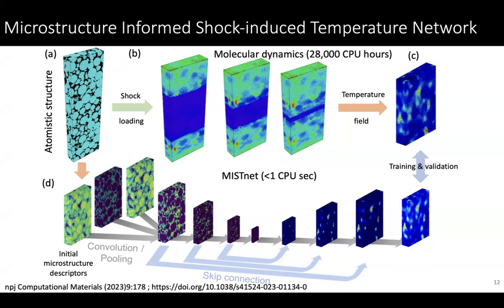But what these guys do is they have convolutional layers. So the convolutional layer looks at, in this particular case, a 3 by 3 by 3 matrix of the initial image and extracts features. And then you have pooling, and what pooling does is it takes a group of these and picks salient features. And it just keeps the salient feature. As you pool, you get a smaller and smaller image from where you bring information from further out and further out. So if you have a void and it's close to another interface, with this pooling mechanism, you learn that that's the microstructure, okay? Convolution and pooling.